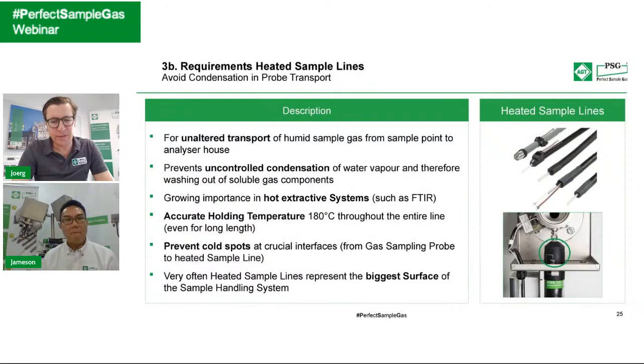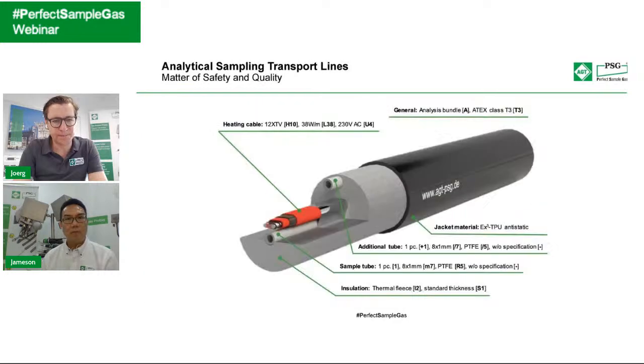Yeah, this is the spot we just mentioned. It's a crucial spot, the connection from the gas sampling probe to the heated sample line. And like we said, a common mistake, Jameson, could be that there is too much space in between, right? Correct, yeah. And that there's no insulation. So if there is no insulation, make it closer, cut the PTFE a little bit shorter, make sure the fitting is well connected, and then try to insulate as much as you can. Always, or sometimes this can be a potential crucial point for creating condensation. Yeah, yeah.